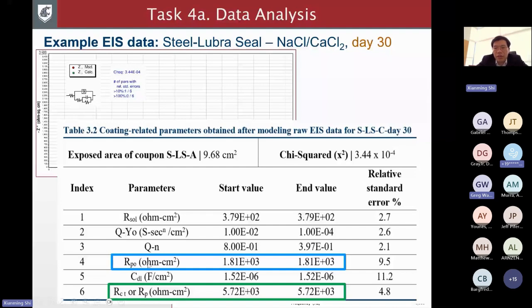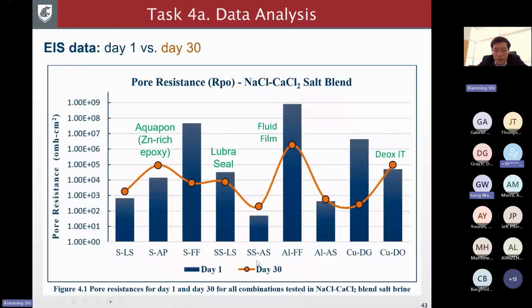Here, as you can see, this is a very busy chart. This is pore resistance for day 1 versus day 30. Day 30 is the curve, and day 1 is the bar chart. And the x-axis is basically the combination of coating and metal. If we consider we need a coating which gives us really high pore resistance, both at day 1 and day 30, then the best product we found was Fluid Film for the aluminum substrate. Following that is the Aquapon, which is a zinc-rich epoxy primer, for the carbon steel. And then Lubra Seal on stainless steel, and then Deox iT for copper substrate. And this is only for the sodium chloride, calcium chloride salt blend.